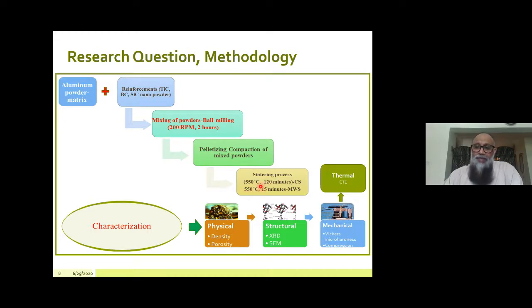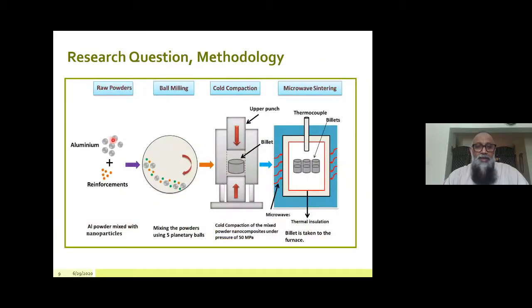Then after the synthesis of the microwave sintered and the conventionally sintered composites, their characterization was carried out. Physical characterization includes density measurement and porosity measurement, and for structural analysis, XRD and SEM images were taken. Then we have mechanical characterization like hardness and strength, followed by thermal characterization. During thermal characterization, the coefficient of thermal expansion was calculated and compared with other materials. So this is the outline of our methodology that was used in the synthesis of various kinds of aluminum metal composites.